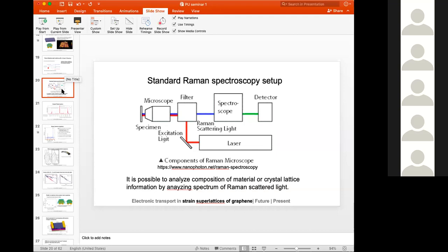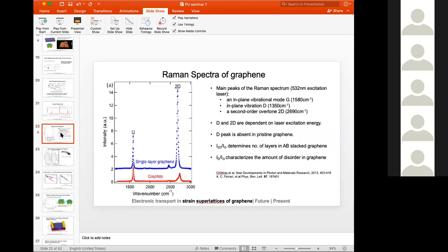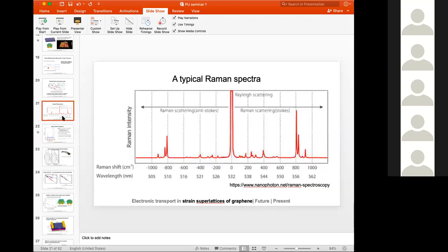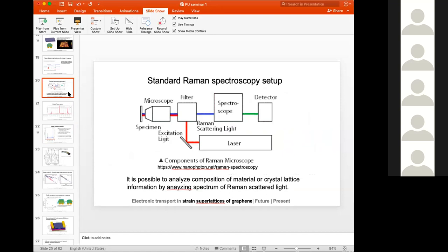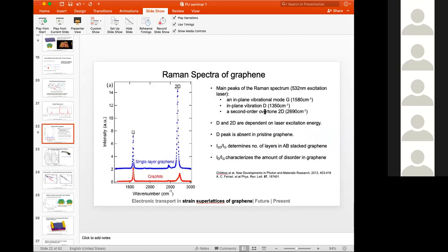So that is a good question, actually. Well, I guess that means I sort of know the answer. The peaks which show up in a Raman spectra are characteristic of the material, right? So for graphene, you know that the peaks are expected to show up in this region. The Raman spectra will give you all the peaks over different wave numbers, but you look specifically in the spectral region between, say, 1000 to 3000, because that is where you'll see the signature of the graphene. And that is how you dissociate the different materials in the structure. Okay, thanks.